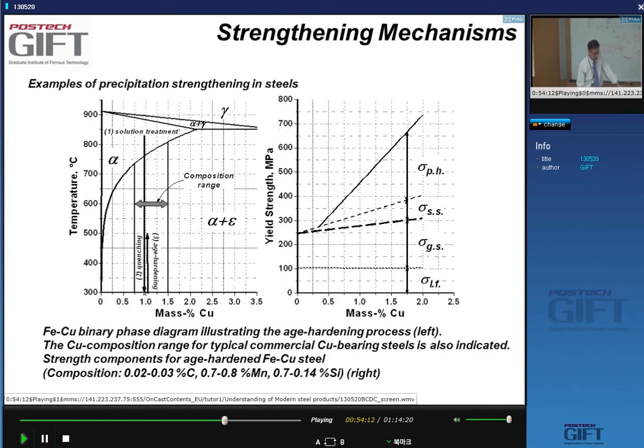When you do this, the copper is in supersaturated solution, and reheating to 500 degrees C results in very small copper precipitates. Yes, if you heat to a higher temperature or for a longer time, you will get coarsening. But at 500, you can get what is called an age hardening steel, where the hardening is through these copper particles.